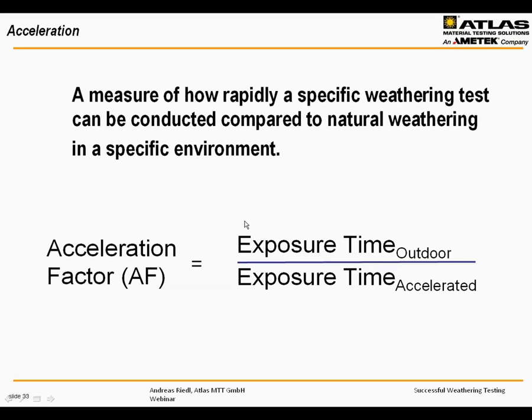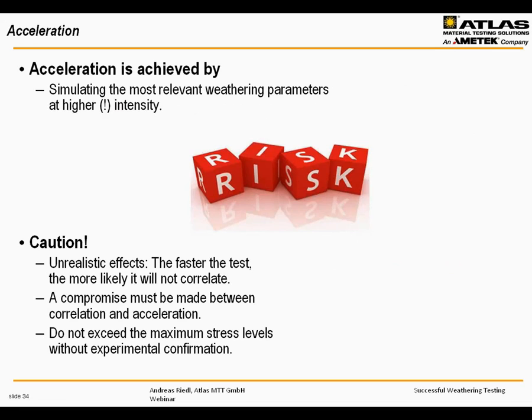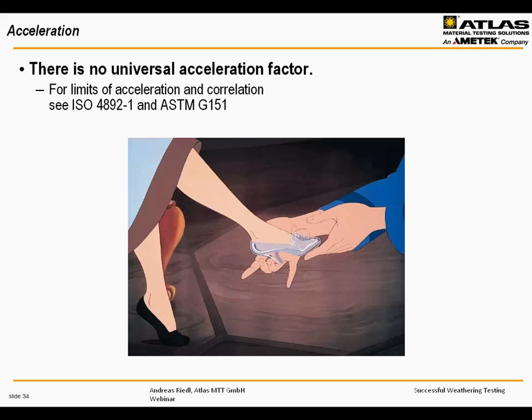Acceleration is achieved by simulating the most relevant weathering parameters at higher intensity, but as mentioned before, don't exceed the maximum values that occur outdoors. Be careful not to intensify the weathering parameters too much. You must make a compromise between correlation and acceleration. Normally, the higher the acceleration, the more risk you put on the correlation, or on the weathering test being realistic or relevant. I have to mention that there's no universal acceleration factor. A very frequent question in weathering testing is, how fast is a Xenon instrument compared to outdoors?